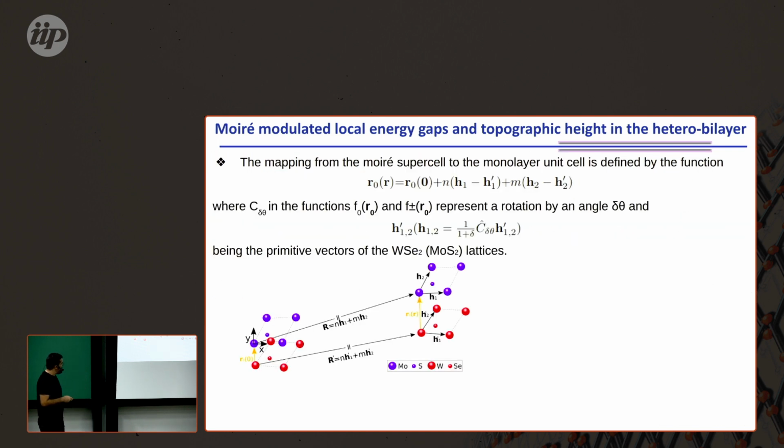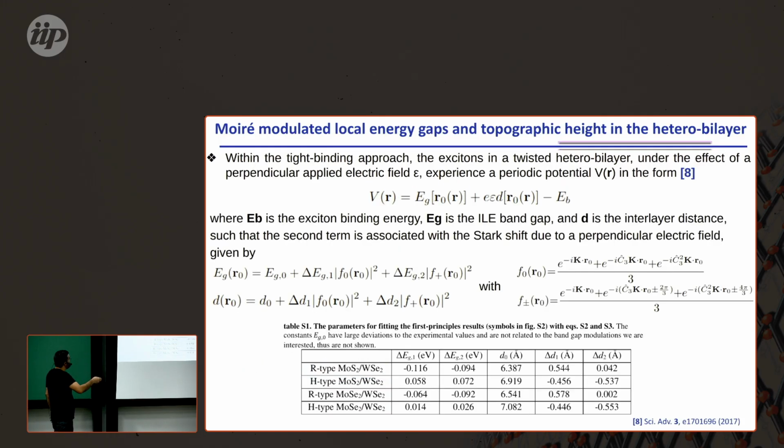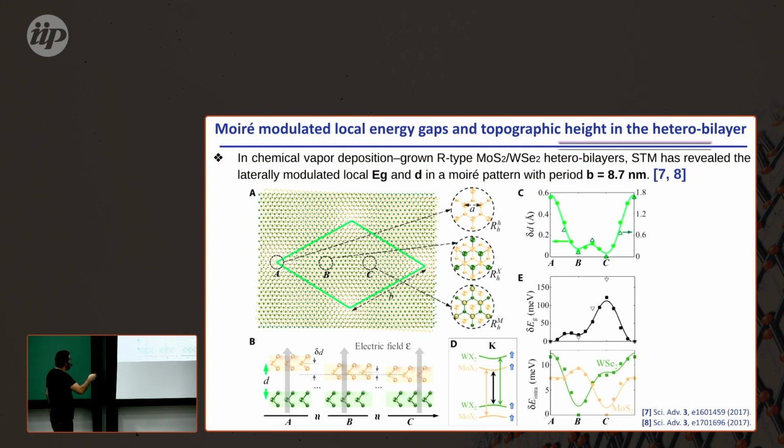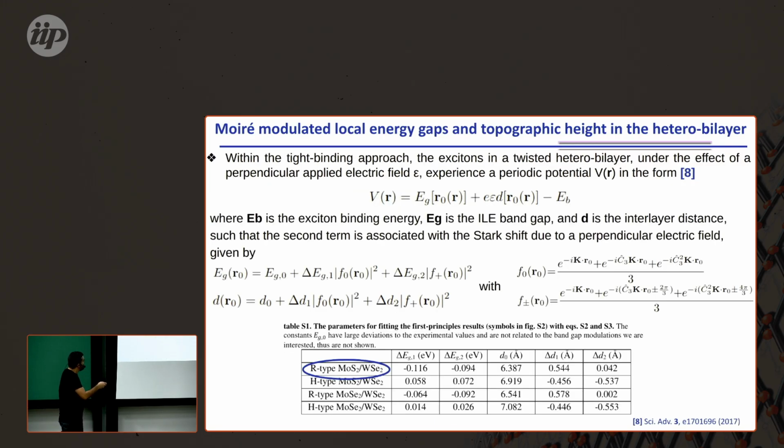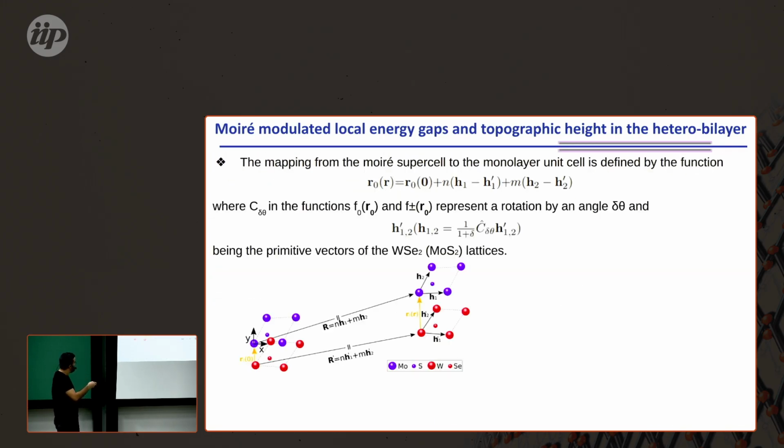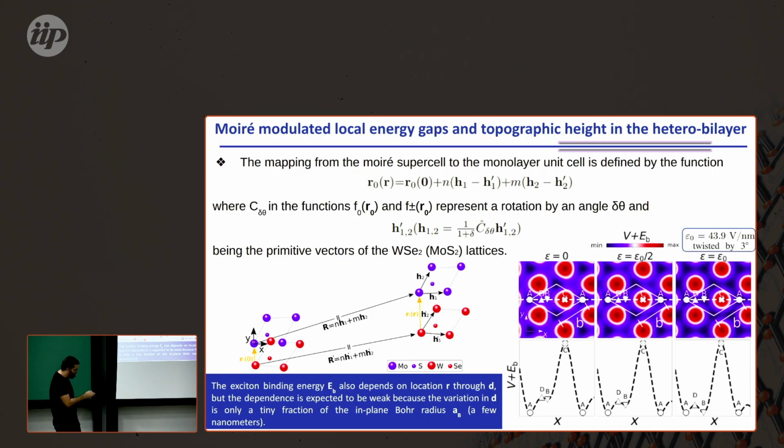And as I was saying, we map this very complicated system of a twisted bilayer TMD as a honeycomb-like lattice where each spot, just to go back a little, each spot here is seen as a sublattice, okay? So by doing this map, we can plot this potential profile, as I'm showing here, for 3 different perpendicular electric fields.